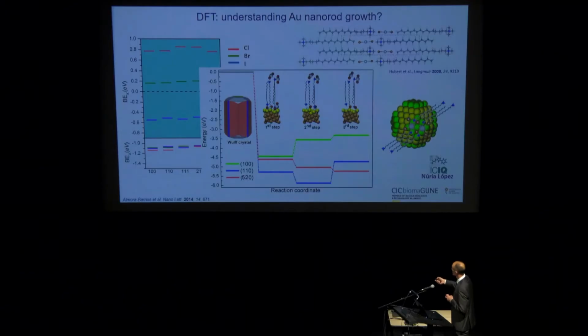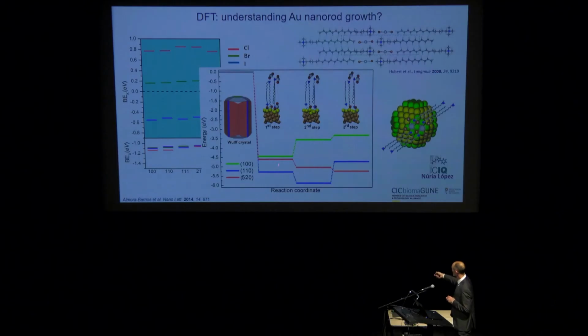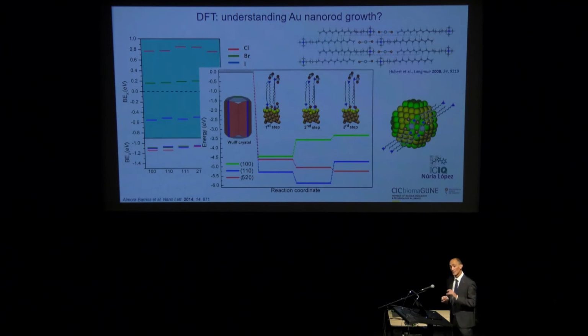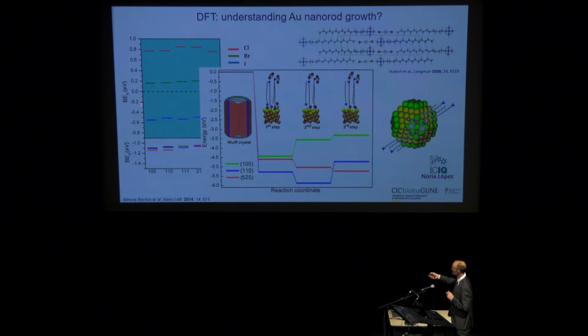And so by following the different energies for different facets in the different steps during the growth of the nanorods, we can see that the 520 facets get more and more stabilized when you are depositing gold and silver ions. I didn't mention them, but they are necessary to make the single crystal nanorods in the presence of bromide. And bromide is, again, a very crucial ingredient in the system. I don't have time to talk about this, but bromide is very important, because the binding energy is in between chloride and iodide. And so bromide can actually bind and get released from the surface. So it allows the deposition of the atoms while still protecting the surface.